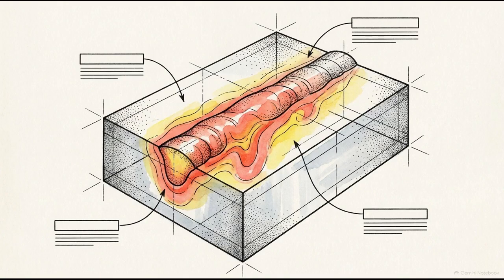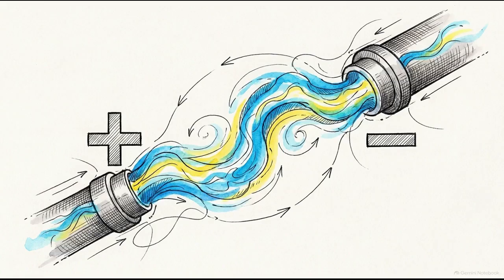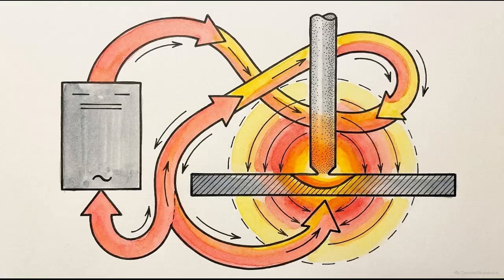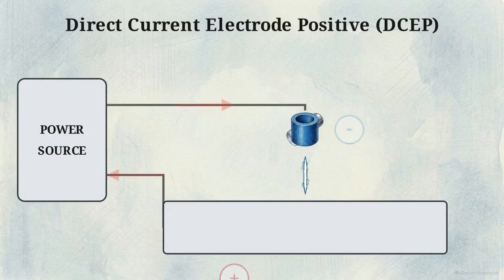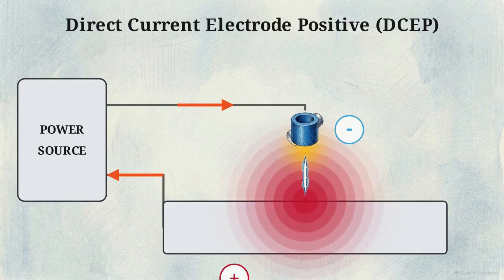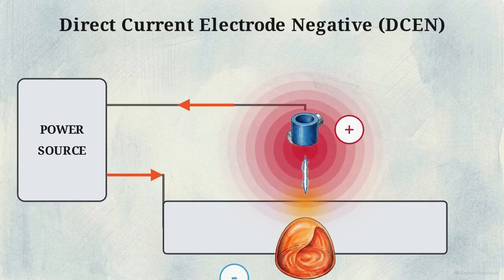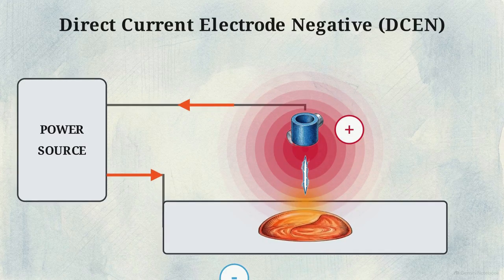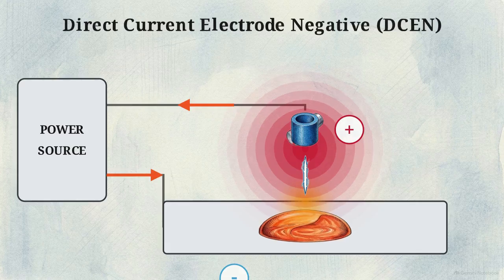Through subtle adjustments in wrist angle and height, the operator directly controls the voltage, dictating the exact thermodynamic footprint of the weld. Alongside arc length, the operator must manage polarity, the specific direction of the direct current flowing between the electrode and the workpiece. In direct current electrode positive, or DCEP, the positive terminal generates 2/3 of the total heat. DCEP drives this thermal energy downward into the base metal for deep penetration. Reversing the flow to DCEN concentrates that heat onto the rod itself, resulting in faster deposition but shallower penetration.